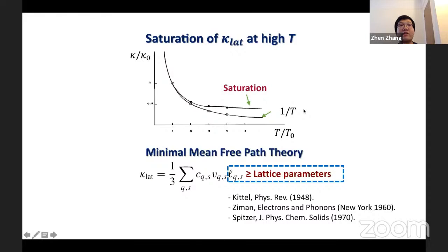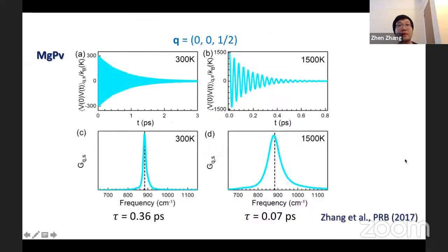relation. However, after careful thought, we realize such minimal mean free path theory does not hold true. The optical phonon branches at the Brillouin zone center usually have 0 group velocities. Phonon quasiparticles with 0 or close to 0 velocities can certainly have mean free path lower than the lattice parameter. This makes the minimal mean free path theory a myth. Apart from the velocity perspective, we also did not observe the saturation behavior of phonon lifetimes at high temperatures.